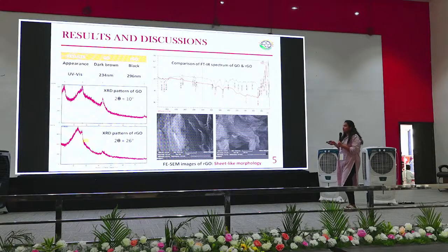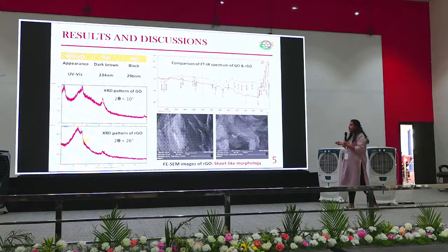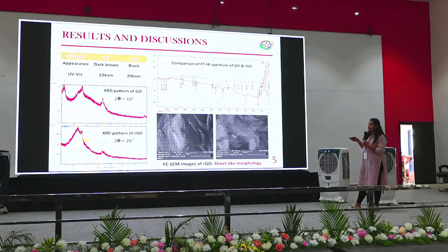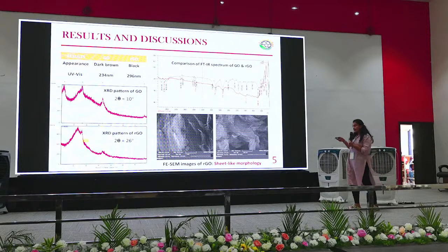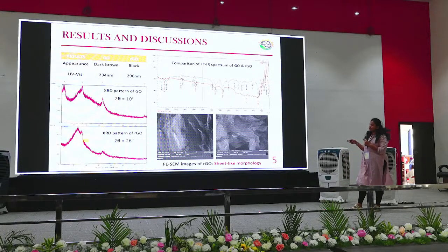In the XRD pattern of GO and RGO, there is a shift from 10 degrees to 26 degrees, and the restacking of the graphene oxide has been reduced. The FESEM images show a sheet-like morphology, which will be apt for energy storage applications.